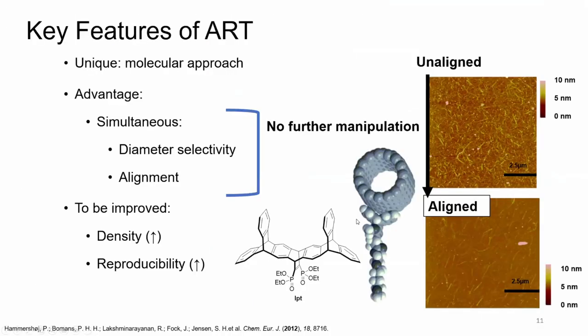All right. So basically, ART presents a unique molecular tweezer approach to aligning these carbon nanotubes, wherein we can also select for different types of tubes. The selectivity between semiconducting and metallic that I mentioned before actually comes from the diameter of the CNTs, and that diameter selectivity comes from the structure of our iptycene molecule here. So the shape of the tweezer can help dictate our selectivity of the nanotubes, and the combination with the liquid crystal and the ART technique aligns the CNTs on the surface, as we can see from the atomic force microscopy, the AFM images here.